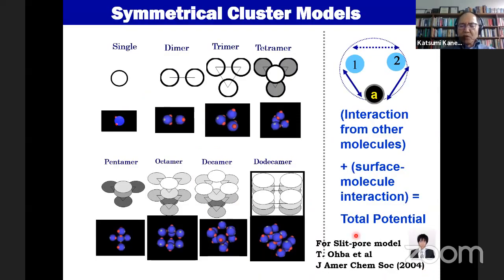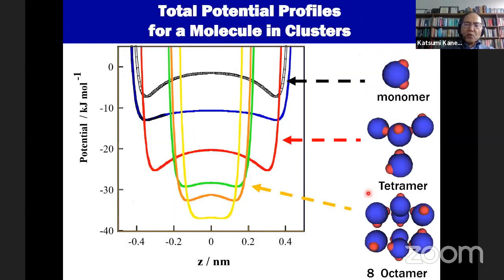Then when this work was done in Chiba, Tomo Oba, who is now working in Chiba, evaluated the interaction potentials, molecule-molecule interaction and the molecule-carbon wall interaction, using symmetric clusters. Then he obtained very interesting total potential profiles for molecules in clusters. A single molecule has a not so attractive interaction potential, very tiny, because the carbon surface is not perfectly hydrophobic, so it is slightly attractive.